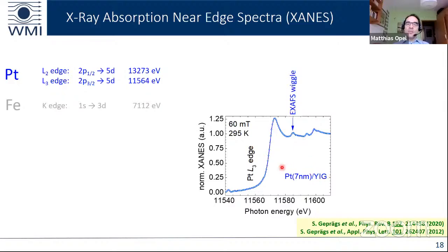What you see here are measurements from 7 nanometers of platinum on a YIG layer. You see clearly an absorption edge here at an energy of 11,564 electron volts. So that means this is the absorption edge of platinum. So you see here the absorption of platinum. Moreover, you see some small structure here. This is called an EXAFS wiggle, and this wiggle is something characteristic for metallic platinum, and it would be absent in platinum oxide. We investigated 3 different samples.